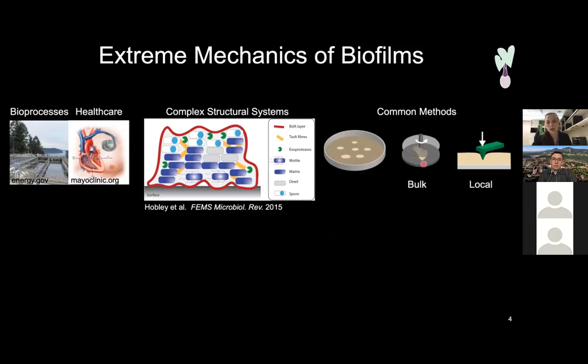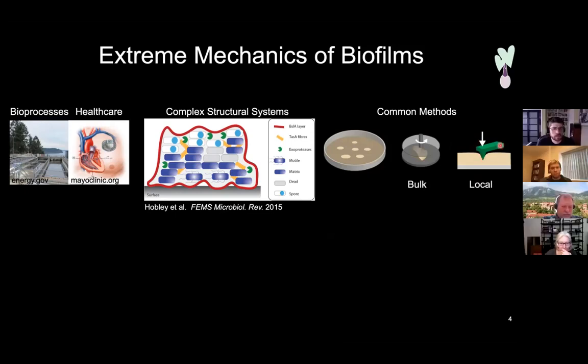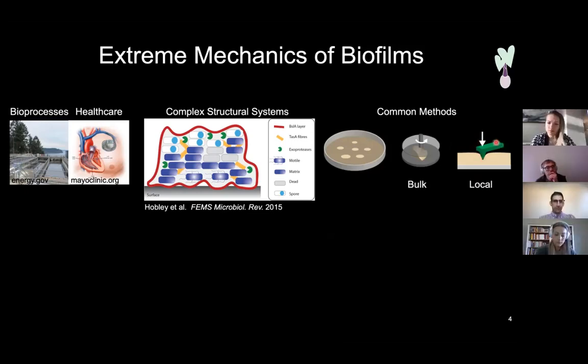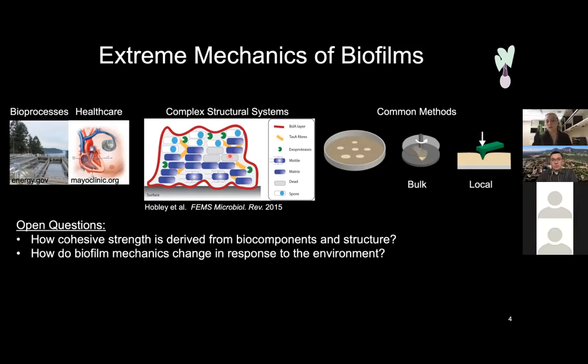But the issue with that is that even biofilms are dependent on what substrate they grow on. They can change their mechanics just depending on the stiffness of the substrate. So that's an interesting thing to probe. The other approach, if you want to probe local properties, is microcantilever testing or AFM, where they do compression or local tensile measurements, but they're only looking at that top layer and those properties, so they can't access that hierarchical structure again. So really these gaps and open questions are, one, what is this cohesive strength and how does it relate to these complex, hierarchical structures?